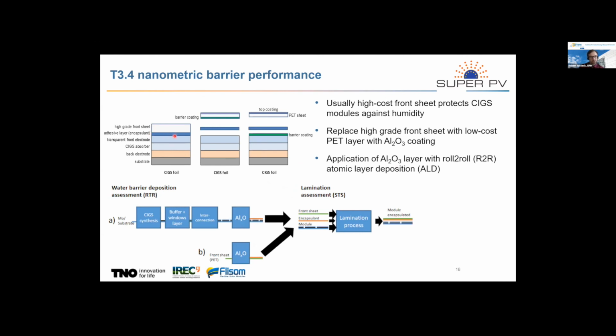The idea here is that usually for a CIGS module, you have a high-grade front sheet, and this is usually very costly. This front sheet protects the CIGS and the contact against moisture. The idea here is to replace this high-grade front sheet, which is costly, with a low-cost front sheet, which is based on PET and coated with an aluminum oxide layer. This is one approach. The other approach would be to directly coat the CIGS layer and then apply this PET layer to the CIGS module. This can be implemented straightforwardly in this production line by this ALD process, either on the CIGS layer or on the front sheet, and then the backend lamination process.